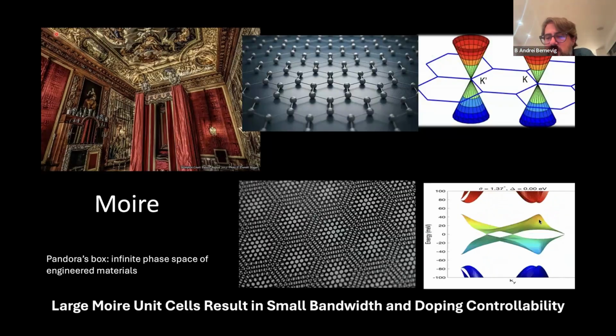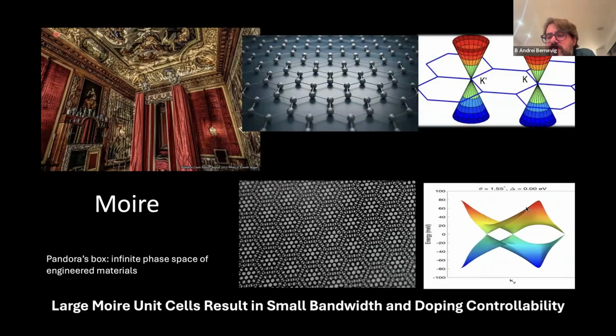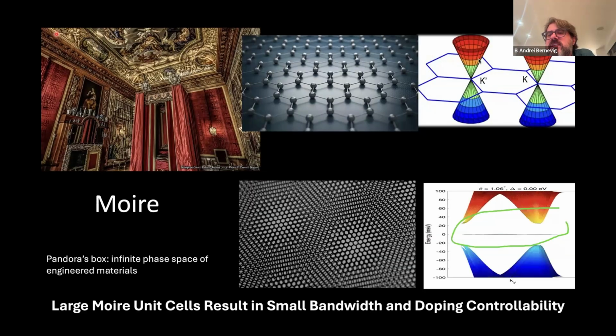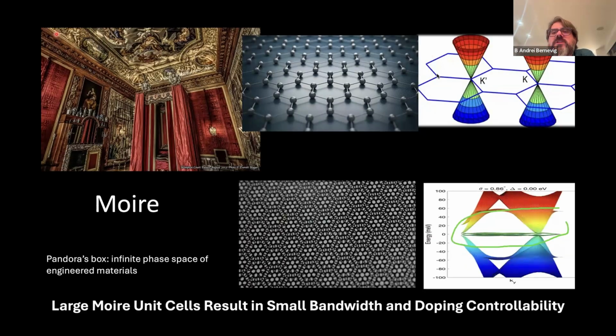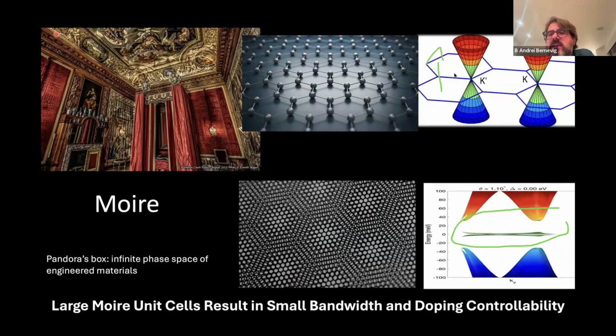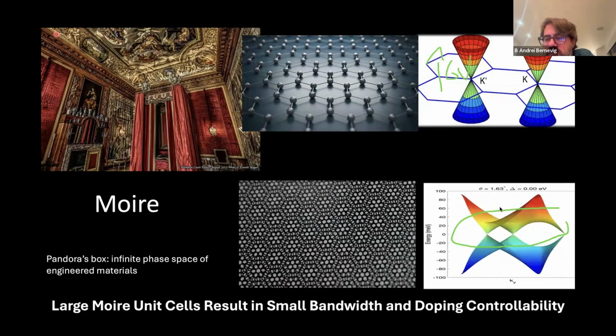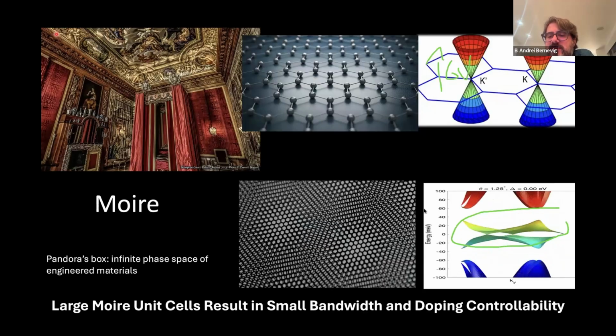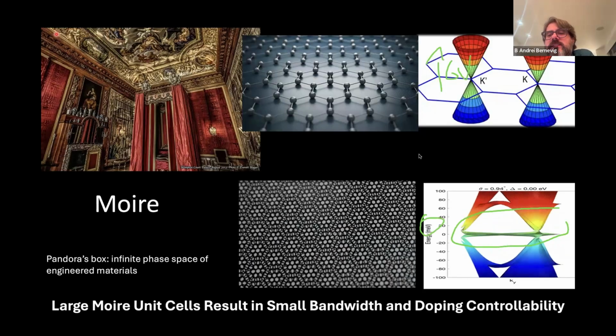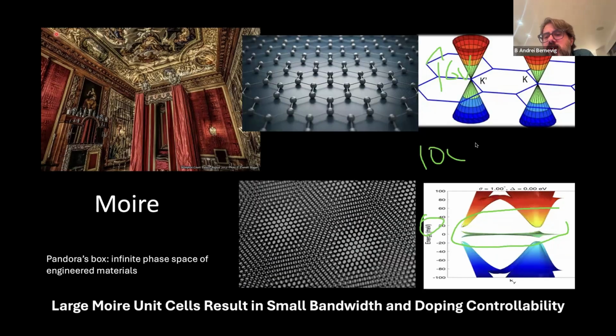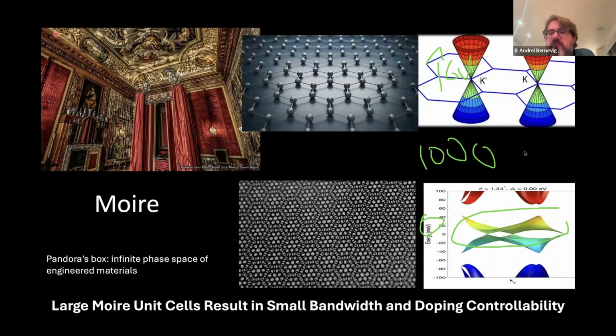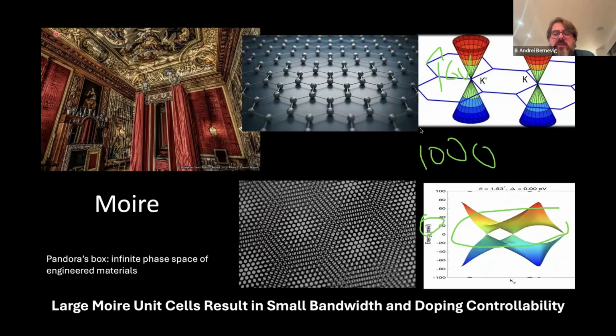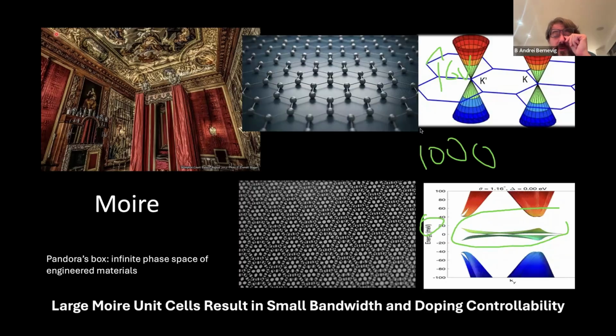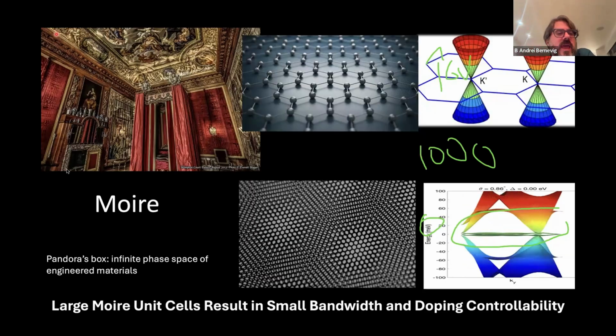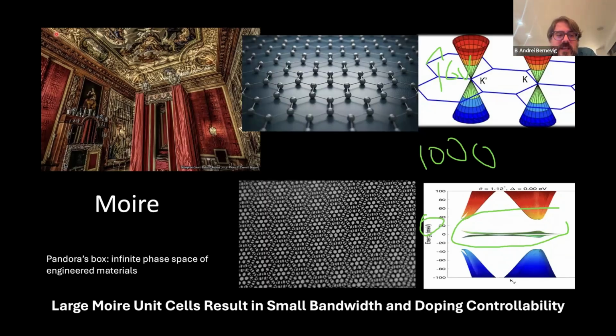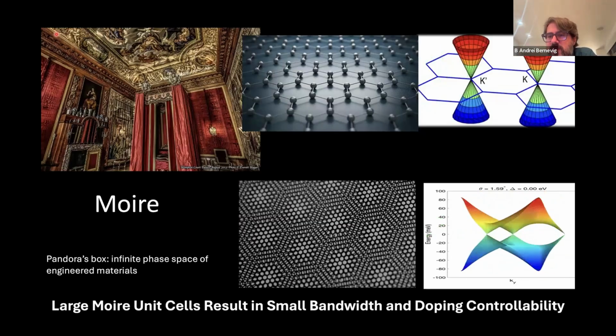And remarkably, what happens is that the bandwidth of these 6 electron volts that I've argued exists here transforms into a bandwidth of 6 milli-electron volts. So it's a 1,000-fold reduction of the kinetic energy. Okay, so the kinetic energy has reduced 1,000-fold just by doing these small things. And that means that now we have a chance of interactions becoming important.